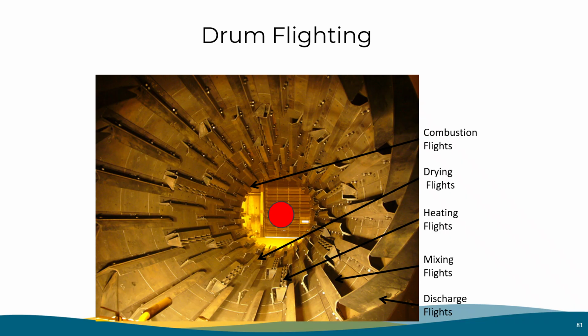Combustion flights are flat and close to the outer shell. Material moves under the burner flame using combustion flights. As a result, the material is heated but does not make direct contact with the flame. Drying flights. The dryer flights remove moisture from the material. Heating flights. Once the moisture is removed from the material, it can be heated to the desired temperature.